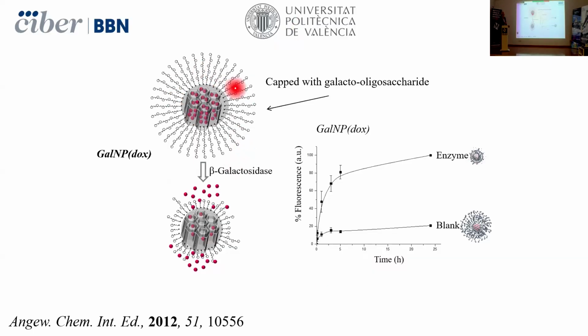This is a mesoporous silica nanoparticle. In that case, it's loaded with doxorubicin, and it's capped using a galacto-oligosaccharide. So you put those nanoparticles in a buffer. This is the delivery profile. There is a poor delivery of the cargo. If we do the same experiment in the presence of beta-galactosidase that is able to hydrolyze those galactose-galactose bonds, then in that case, there is a delivery of the doxorubicin.